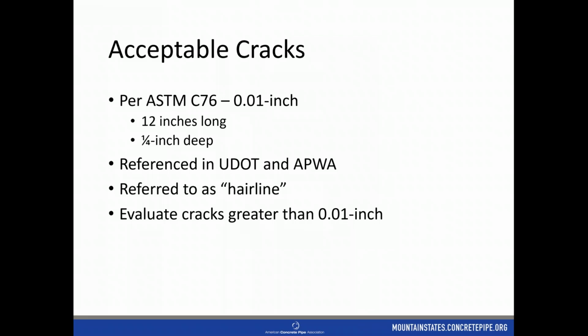What caused this to crack? Was it construction loading and now it's seen its full load? Is it continuing to crack because it wasn't installed correctly to handle the traffic loads above it? What's causing this problem? What are the issues? You've got to ask a lot of really pointed questions to get to the bottom of what caused this crack in the first place, because two cracks that look the same may not be the same, just because of what's causing them. If one is caused by significant loads early on and it hasn't seen any loading since, that's different than one that is continuing to be subjected to heavy loads and is continuing to increase in cracks. So you've got to ask these questions and try to find things out.